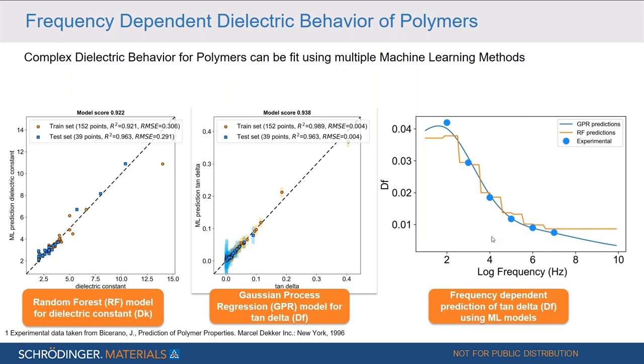We can also look into the frequency-dependent prediction of the dissipation factor, which is shown here on the right-hand side. So we see the results for the random forest algorithm in orange, and for the Gaussian process regression in blue, compared to experiment. The experiment is denoted by the blue filled circles here. We see that we actually observe a quite good agreement between experimental and predicted values.